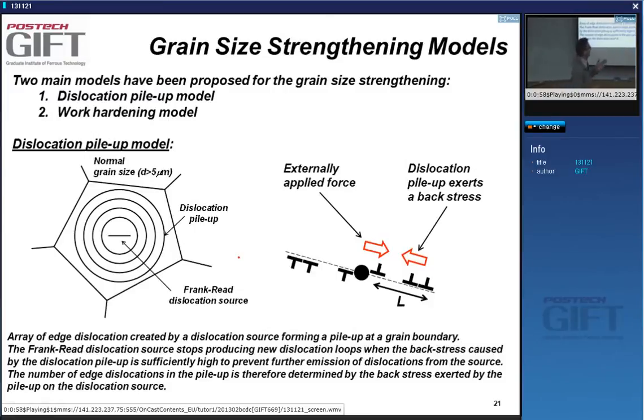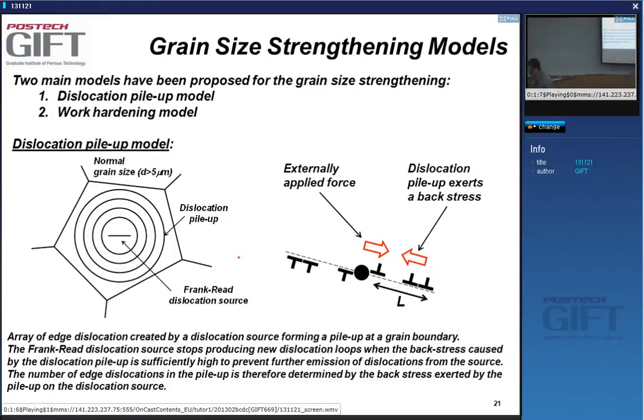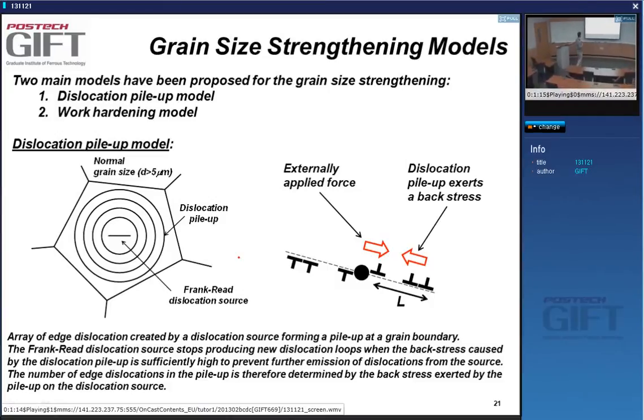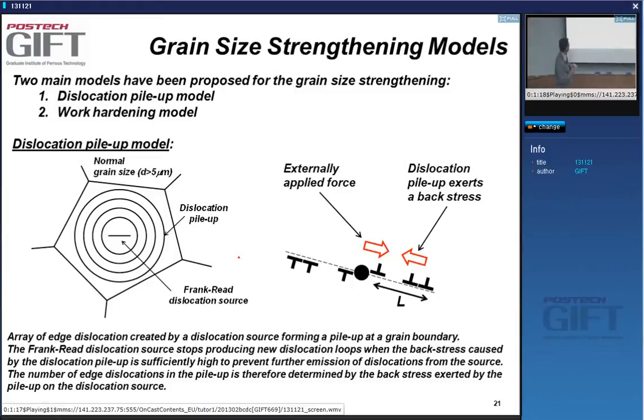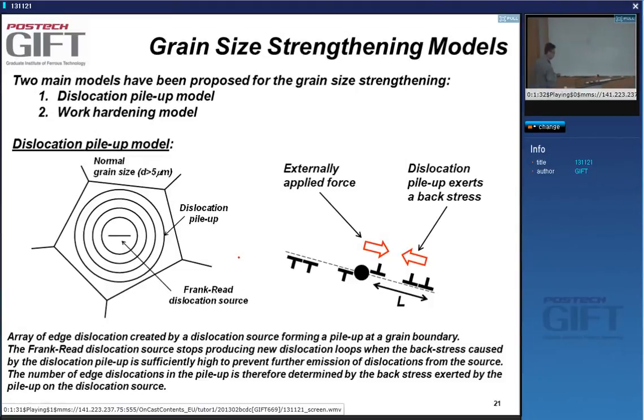The size of this back stress will be determined by the number of dislocations in the pileup. The Frank-Read source will stop producing dislocations when this back stress is large enough to prevent further emission of dislocations from the source. The number of dislocations in the pileup is determined by the back stress.